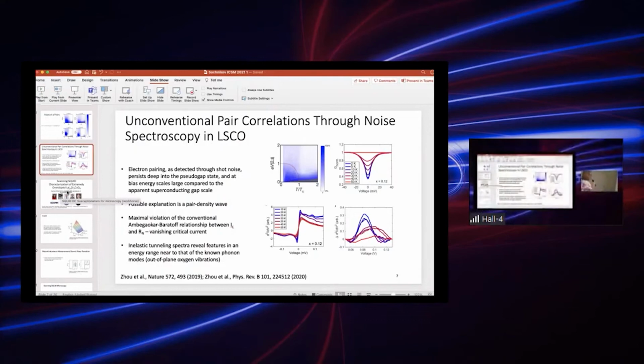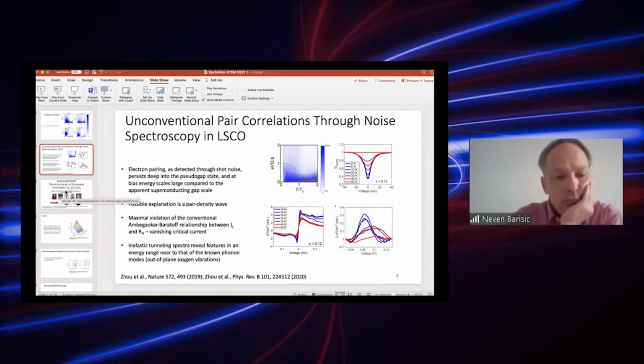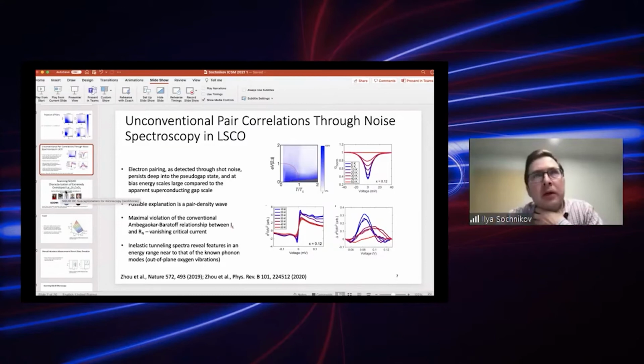Well, for the junctions part, the problem that may arise is that if you get not very high quality junctions, you're just going to get leakage current. So LSCO films are basically grown as perfectly as they can be by Ivan. So that's kind of the reason for the choice. But of course, there are deeper reasons.